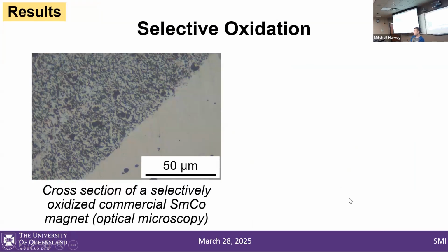This is a cross-section, a zoomed-in polished cross-section of one of our selectively oxidized magnets. In the top left, you have our selectively oxidized zone—the dark spots are your oxide particles, and the light spots are your cobalt and iron metal particles. In the bottom right, you have your unreacted samarium cobalt.